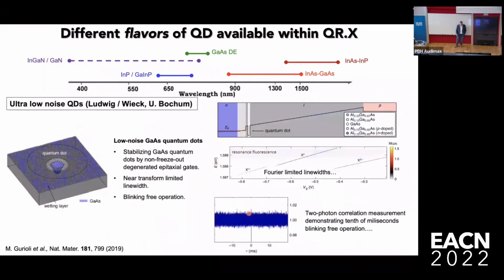And then finally, there are also very interesting, I wouldn't call them new approaches to making quantum dots, but strain-free quantum dots made using gallium arsenide. This is what's called droplet epitaxy. To give you some idea, these quantum dots do not have indium in. That makes the coherence of spin qubits better. At the same time, they have fantastic stability, so they don't exhibit blinking. Over here, you see tens of millisecond timescales, beautiful anti-bunching for zero time delay, and the line widths are fantastic. So these types of quantum dots in stabilized device geometries are these days extremely important.